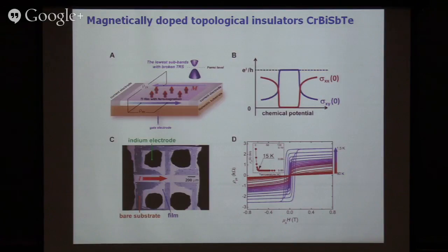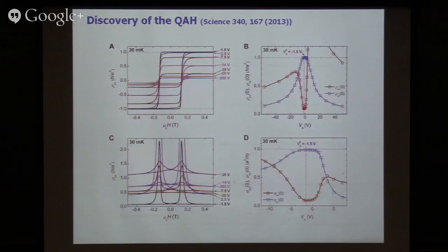So what exactly is the experimental signature? Now you grow on a substrate this topological insulator film, but this time not only putting in bismuth telluride, but also some amount of chromium into the system. And now you measure the Hall resistance, the transverse voltage divided by the longitudinal current, as a function of magnetic field. First, when you see a hysteresis loop in the Hall effect, it's a very good indication that the material is ferromagnetic. But most interestingly, when you look at this hysteresis loop at zero external magnetic field, there's still a quantized Hall effect. The magnitude of this is 1 in units of h over e squared, which is the resistance quantum in basic quantum mechanics.